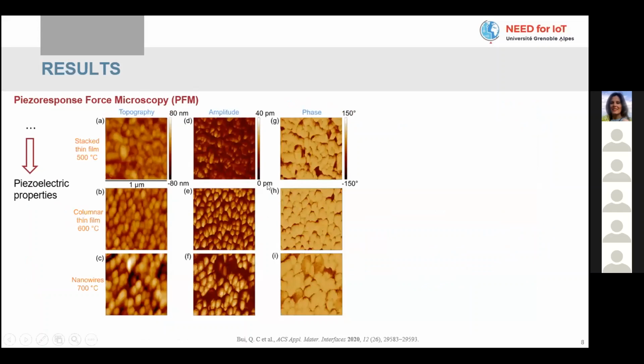So here what I want to show is the piezo performance of the zinc oxide with different morphologies: the thin film, stacked thin film, columnar thin film, and nanowire, with similar thickness and similar length on the nanowire. We can see the topography from the AFM technique, and we have the amplitude of the displacement of the zinc oxide when we apply the voltage. And we see that from thin film to nanowire, the signal is brighter. It means the piezo signal or displacement is stronger, or the efficiency is higher.